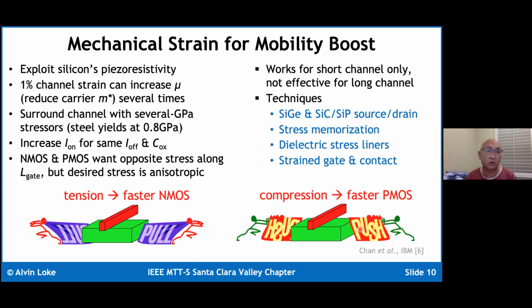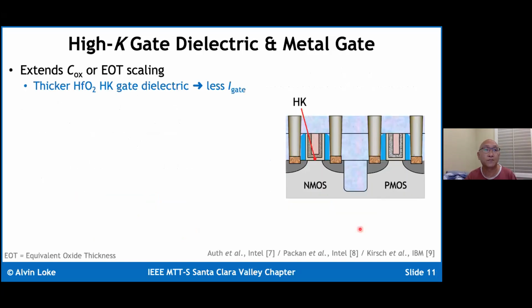For employing or incorporating mechanical strain in the transistors. Okay, the other technique that's used is a HighK gate dielectric and metal gate. The idea here is that we want to essentially extend the COX scaling, try to make COX larger and larger. One way of doing that is to replace the nitrided gate oxide material with a hafnium oxide HighK dielectric material, which has a much higher permittivity, which means that for the same COX, you can make it a lot thicker.